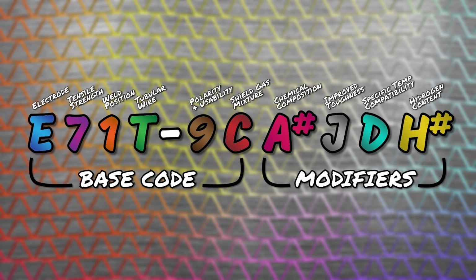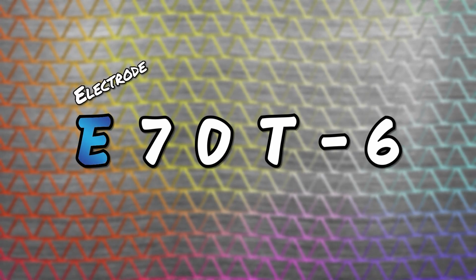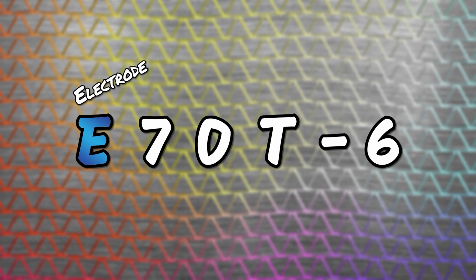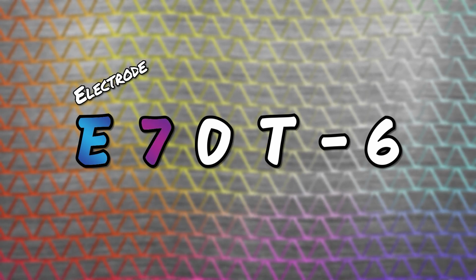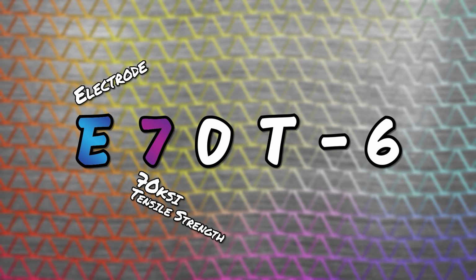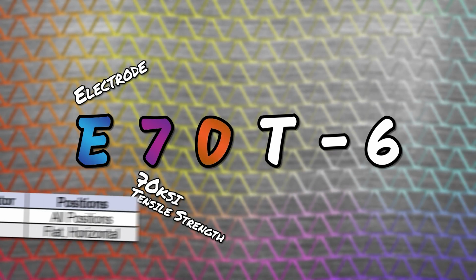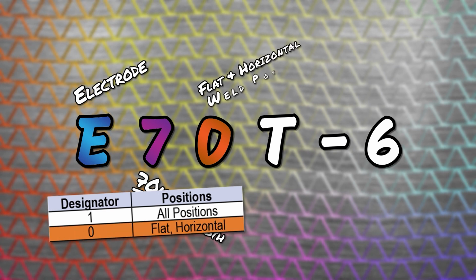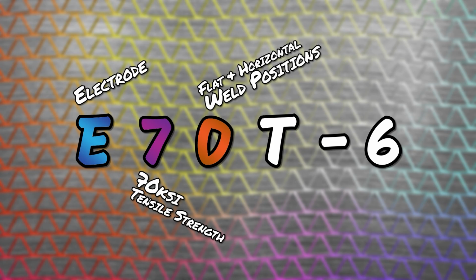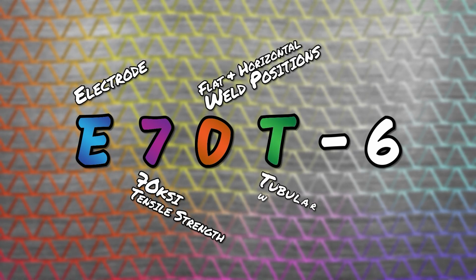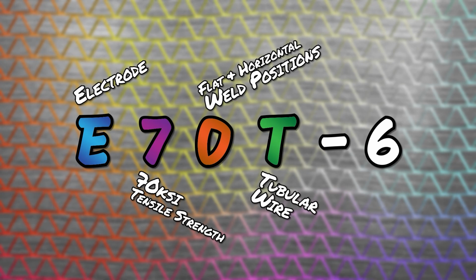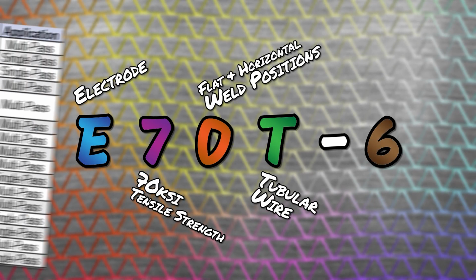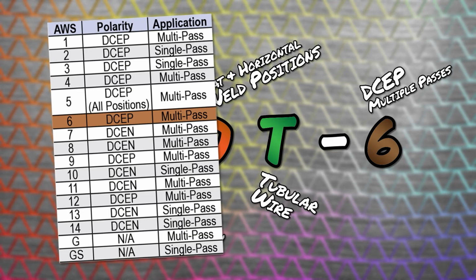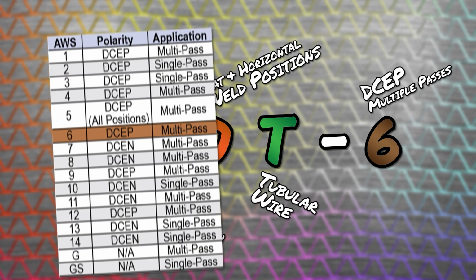Let's read a few codes for FCAW. E70T-6. E means that this is an electrode. The 7 tells us that this product has 70 KSI of tensile strength. The 0 means that this can only be welded in the flat and horizontal positions. The T tells us this is a tubular wire. And the 6 informs us that the required polarity is DC electrode positive and will be good for multiple passes.